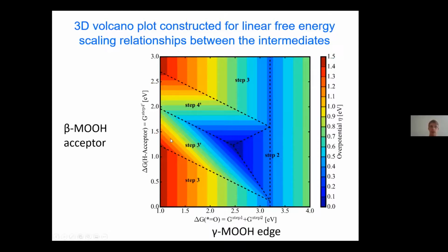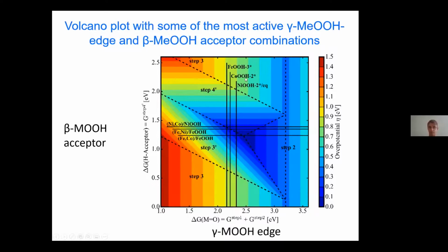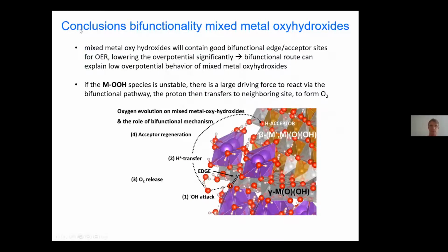So what happens now if we plot the most active edge systems and acceptors on this graph? Then here, if we take the most active edge systems and we combine them with the most active acceptor sites, we see why the overpotential is actually getting lower when we work with three metallic systems. And that's because we have a bifunctional mechanism that is operative. So that's basically the conclusion of this work, that bifunctionality explains why mixed metal oxyhydroxides are active.